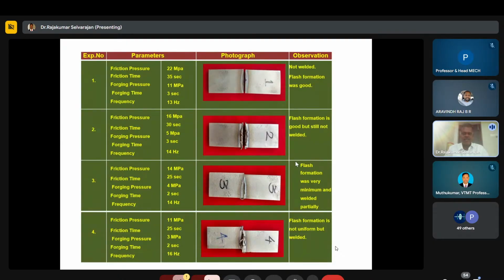Then we are increasing the forging pressure to 4 megapascal, with 3 to 4 seconds, and reducing the forging time. So flash formation was very minimal and it welded only partially. Partial welding has taken place, and then we reduce the friction pressure and increase the frequency to 16 hertz. Then you can achieve it. You can see that flash formation is not uniform, but it is welded.